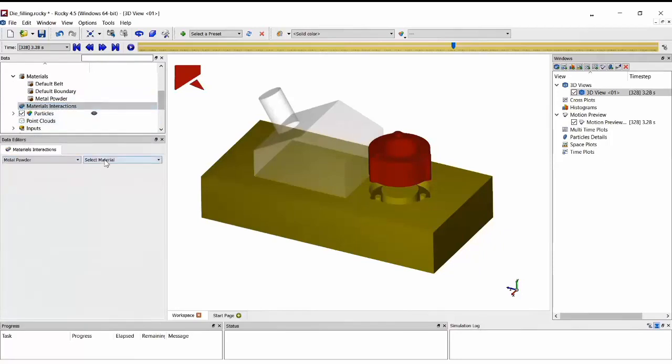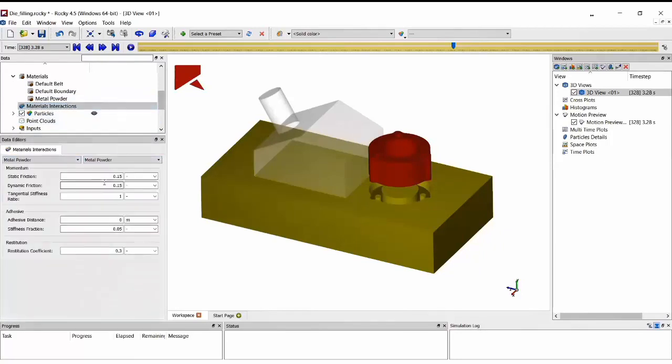particles. Next, we need to define the interaction parameters for our simulation. What is important here, for example, is the interaction between metal powder and powder, which is particle-particle interaction. We added some type of adhesive force between these particles because post compaction, we want them to hold onto each other. That's how we mimic some type of sintering or fusing of these particles together using adhesive force.